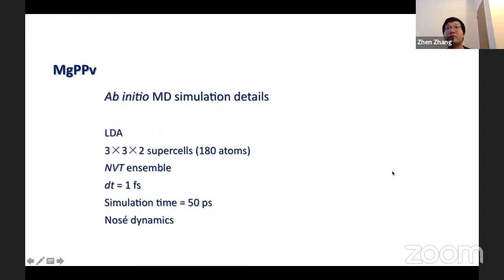Here are the ab initio MD simulation details. LDA was adopted. 3x3x2 supercells equivalent to 180 atoms were simulated in the NVT ensemble. Each MD ran for 50 picoseconds with a time step of 1 femtosecond. Temperatures were controlled by Nosé dynamics.